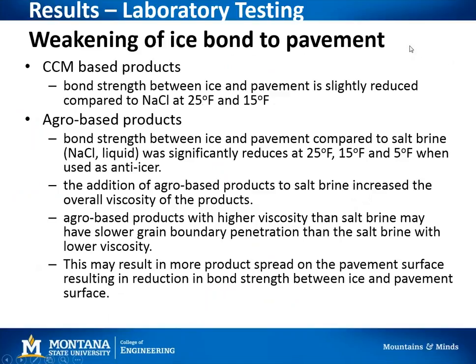To summarize this data: for complex chloride mineral-based products, bond strength between the ice and the pavement was slightly reduced compared to salt brine at the temperatures tested. And for the agro-based products, and this includes category B and category C products, so ag-based products mixed with salt brine, and then the agro-based products as received from the vendor manufacturer, the bond strength between the ice and the pavement compared to salt brine was significantly reduced at all temperatures for all products. And the addition of the agro-based products to the salt brine, so the category B products, increased the overall viscosity of the products compared to salt brine alone. And the agro-based products with the higher viscosity than salt brine may actually have a slower grain boundary penetration than the salt brine with the lower viscosity.